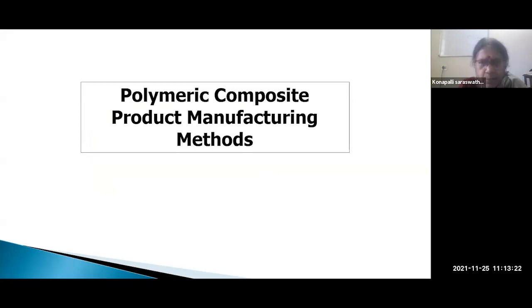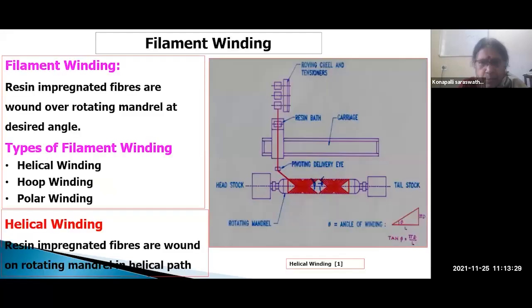Now coming to product, is it time there? Filament winding is the main process. With filament winding technology, we can get cylindrical components, long cylindrical components. Then we can get conical components easily, and not only symmetric, unsymmetric components also we can wind. So filament winding technique. In filament winding, resin impregnated fibers are wound over a rotating mandrel at desired angle. I'm not able to take the cursor, otherwise I could have shown in the figure. Roving from creel stand comes, dipped in resin bath, comes through carriage, and they are deposited on the rotating mandrel. So that is how the filament winding is.